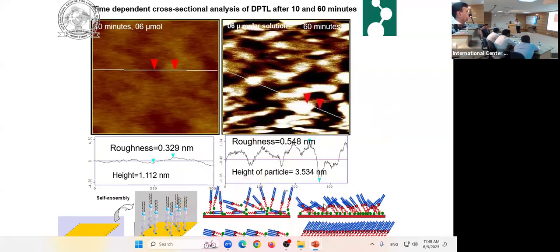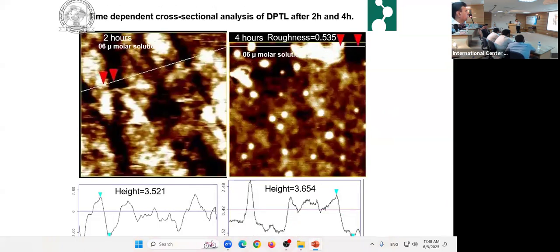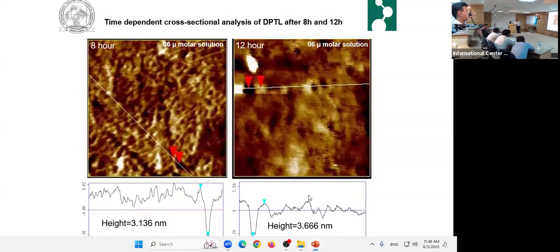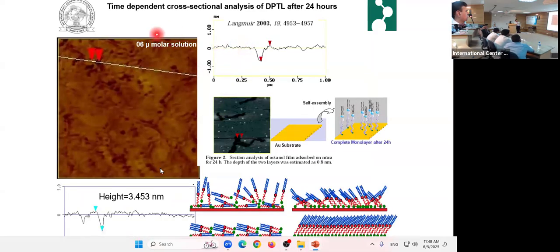Initially it was this, and then this, and with the passage of time it was rearranging itself, but the height was still there, 3.5, 3.6, and now a smoother surface was obtained. This was the surface of this molecule. As you can see, there is a lot of flexibility, because it is important to put your molecule, which can undergo cylindrical assembly through hydrogen bonding, on a surface like this.